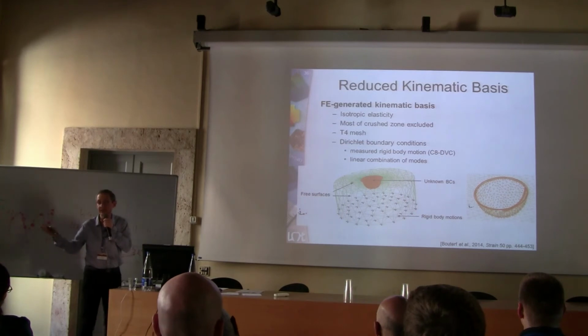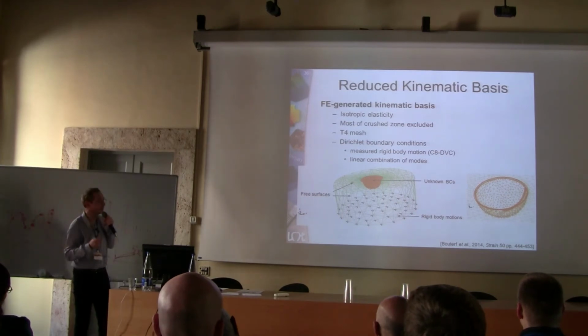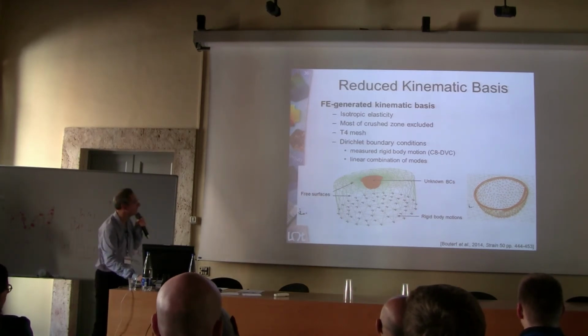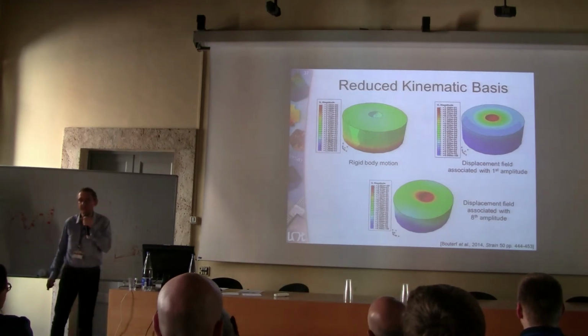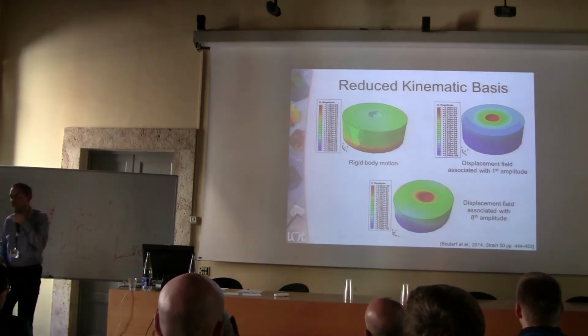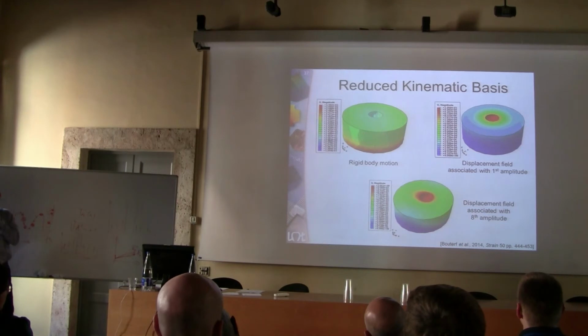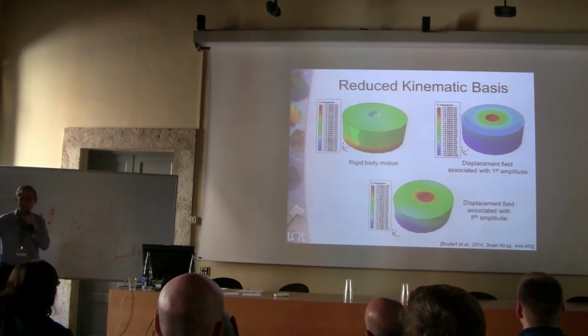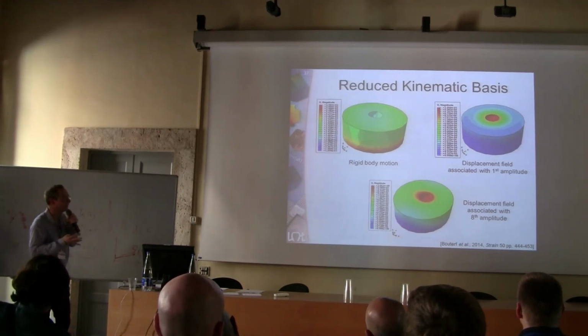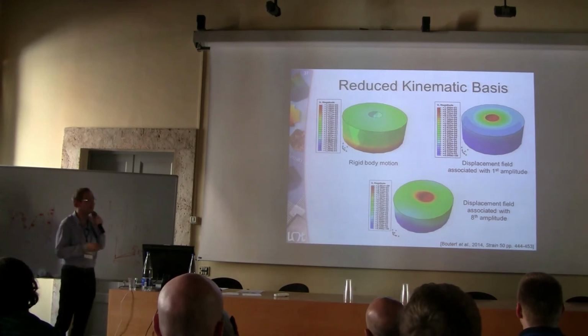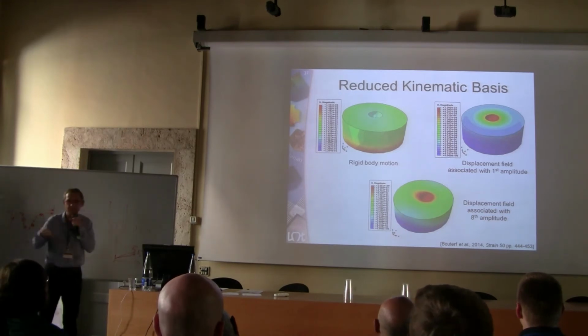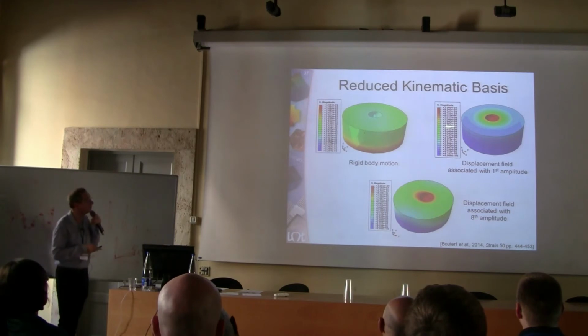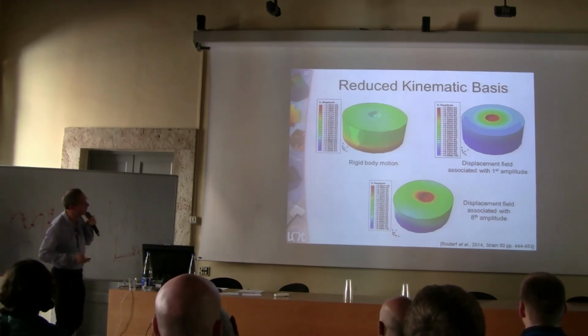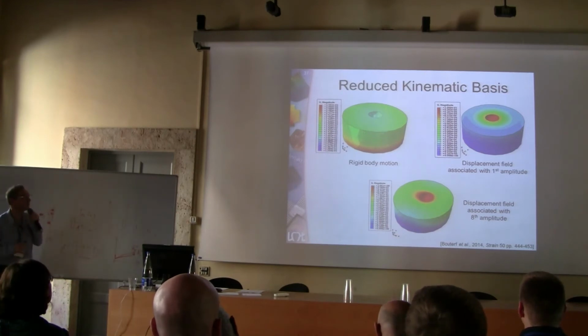Best match meaning that we will control that with the gray level residuals. So we can come up with a reduced kinematic basis constructed with numerical simulations that are totally consistent with the experiment, at least at the bottom part, because we prescribe the measured boundary conditions, and for the top part we determine these Dirichlet boundary conditions with very few amplitudes.